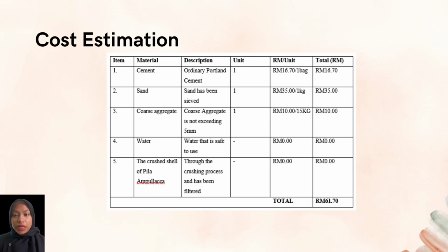For the cost estimate, we estimate for one batch is around 61 ringgit 70 cent, which is for the cement we use the ordinary Portland cement. The unit for one batch around 16 ringgit 70 cent, and for the sand we use around 35 ringgit per 1 kilo. For the coarse aggregate around 10 ringgit for around 15 kilogram. The Pila is free, which is we just take it from lake or from the rice plant.